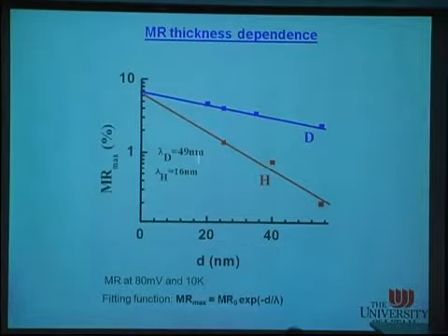And we actually measured the spin diffusion length of those materials, and it turns out that the deuterated D-DOO-PPV has 3 times more diffusion length than the hydrogenated D-DOO-PPV. How was this determined, in the same way, by looking at different thicknesses? Yes. Here we make a few devices with different thicknesses and measure the spin diffusion length, fitting it with this formula. Yeah.